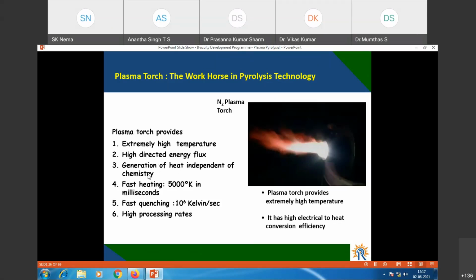without these things; in the graphite arc system, you don't need even gas. So you can generate plasma plume. So fast heating: 5000 Kelvin you can generate in milliseconds. Fast quenching is possible. You can switch off, and this 10^6 Kelvin per second is the quenching. And high processing rates are there. Because of high temperature, Arrhenius equation, as the temperature increases, the rates of conversion become very high. Rate of reactions increases with the temperature. So at very high temperature, your rates of conversion are going to be very high.